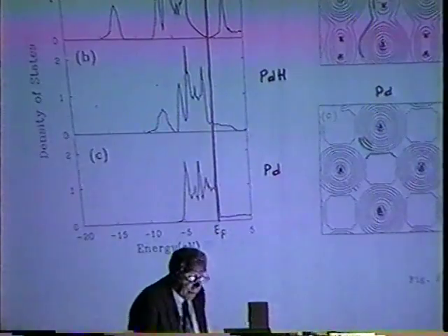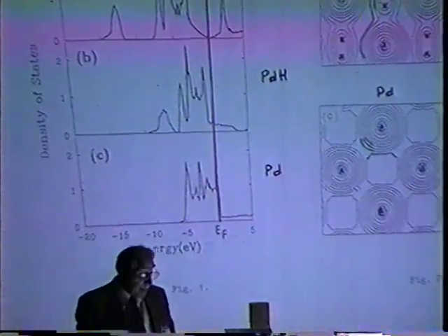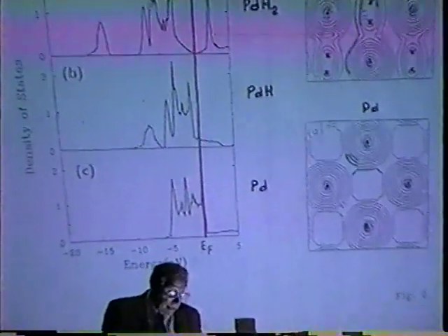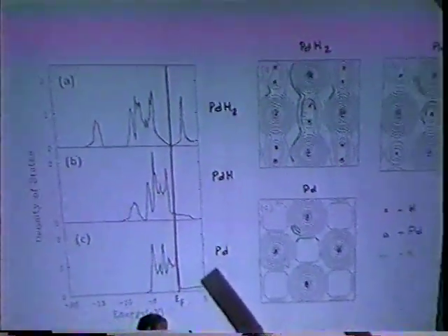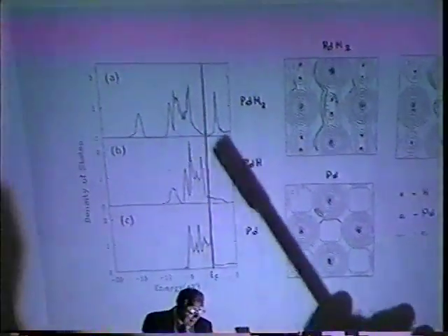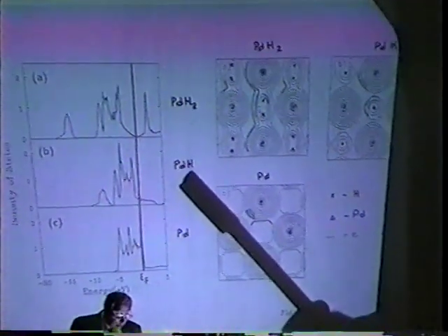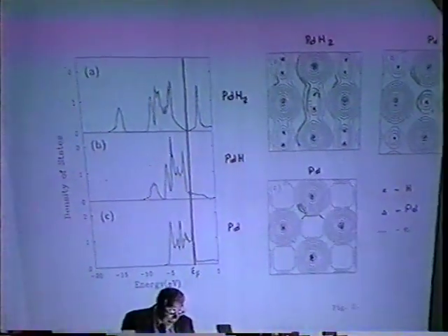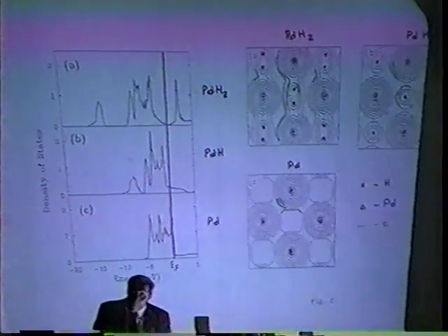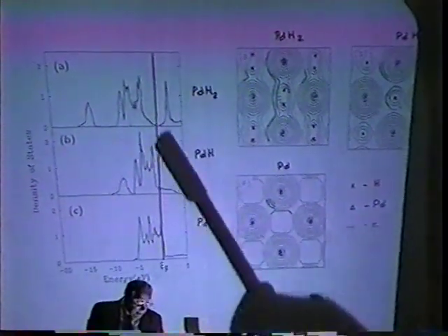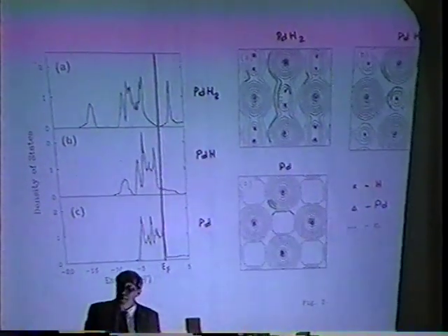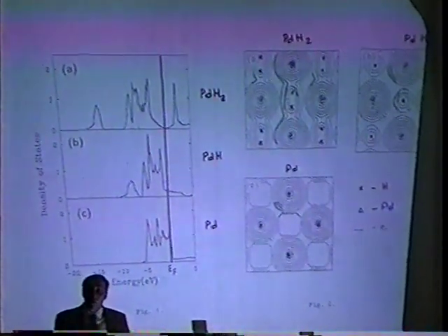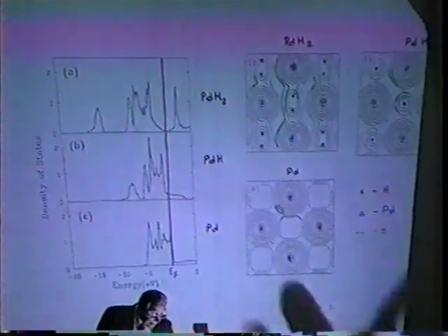I just show you. This is a result from the San and Thomas paper, and they calculate the density of states for palladium, palladium hydride, and palladium H2, and they really observed what we are predicting. They observed a gap, and the Fermi energy is just inside the gap, and it is known that this is a situation of transition to a non-metallic state. And this is shown in this picture also.